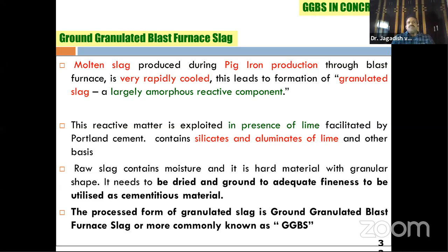So GGBS, as I mentioned, is molten slag produced during iron production, not steel, okay? Very rapidly cooled, slags are formed, and then ground to amorphous form. And this reactive matter, in the presence of lime, forms further CSH gels because it contains silicates and aluminates of lime, and secondary hydration happens. And you have to grind it to adequate fineness, as I mentioned, and then you can use it as a cementitious material. The processed form of granulated slag, we call it ground granulated blast furnace slag. Commonly, we call it GGBS.